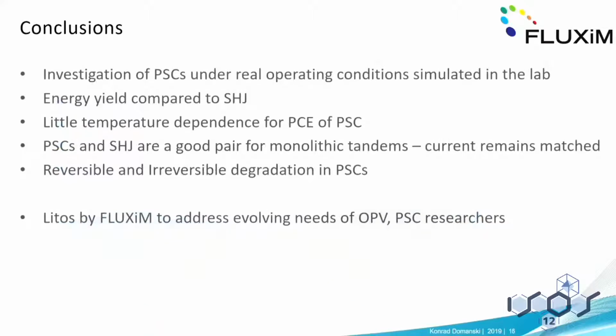And let me conclude: we investigated perovskite solar cells under real indoor-outdoor conditions, if I could say so. And we compared the energy yields with silicon heterojunction. So we established a method to use any arbitrary illumination and temperature profiles from anywhere in the world without physical presence outdoors and simulate it in the lab.